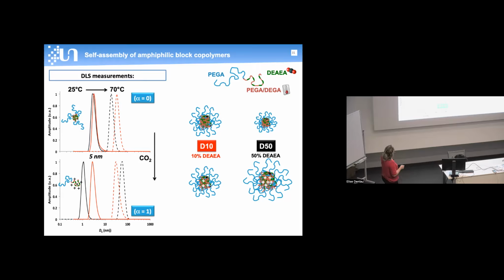So here, when we increase the temperature, we form the aggregates, and before or after CO2 exposure, the behavior is the opposite. Before exposure, again, the amines are in the neutral form, so alpha equals 0. And then we see that when there are fewer amine units, the aggregates are bigger, here in red, because again, for us, at the neutral stage, the amine units are more hydrophobic, so with more hydrophobic units, the core is more collapsed. Whereas upon CO2 exposure, you protonate the amine units, and in this case, you form bigger aggregates with more amine units because the core is swollen by the charge of the amine units.